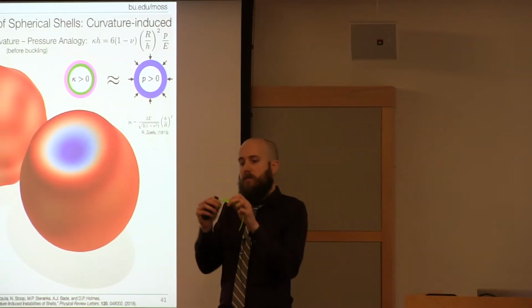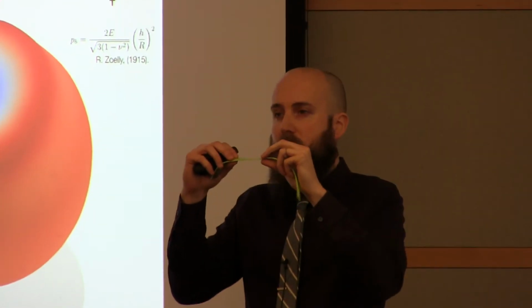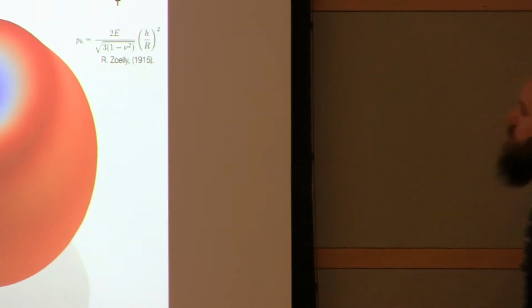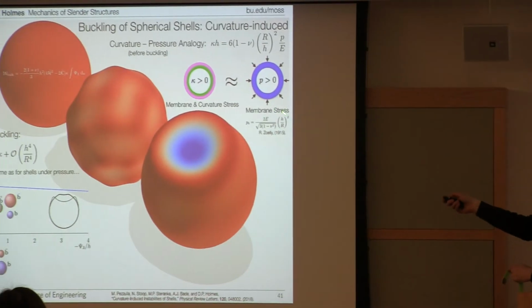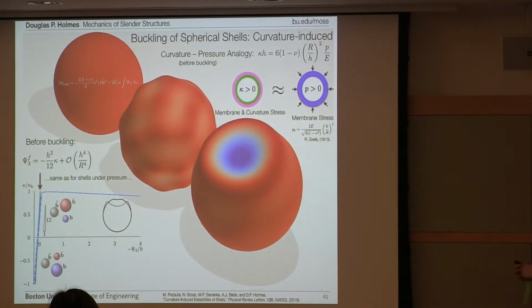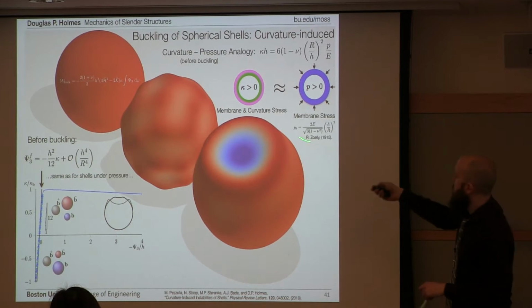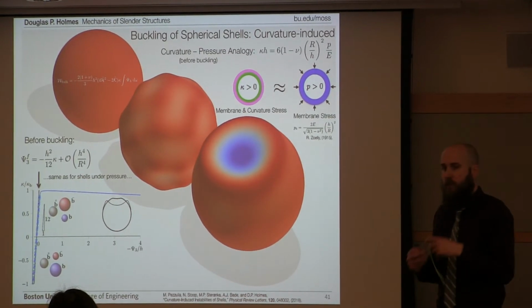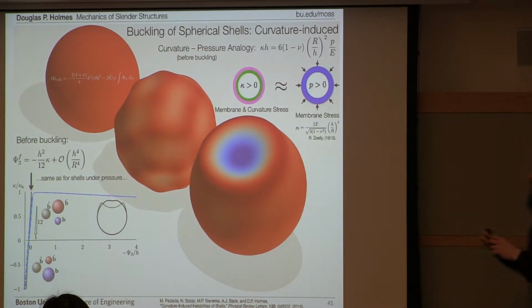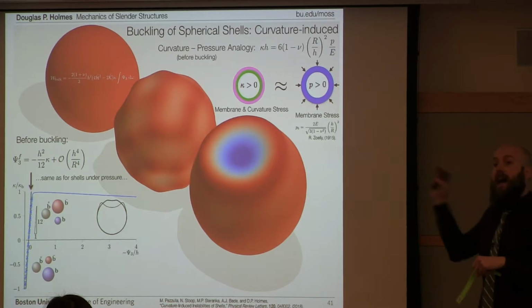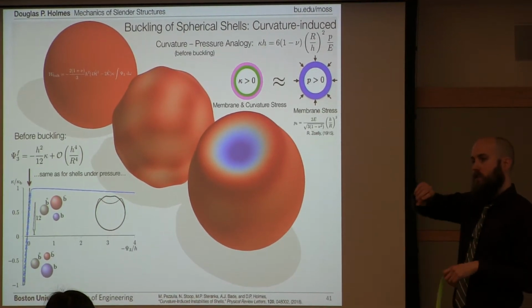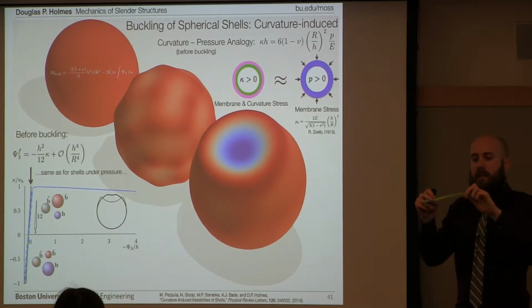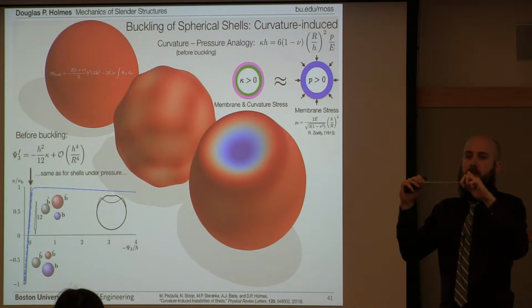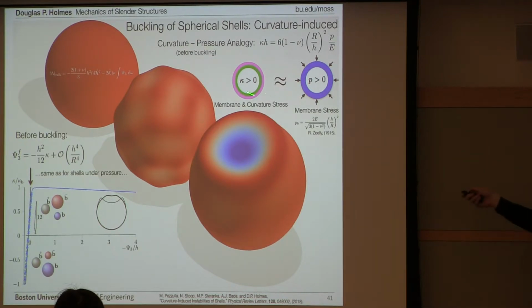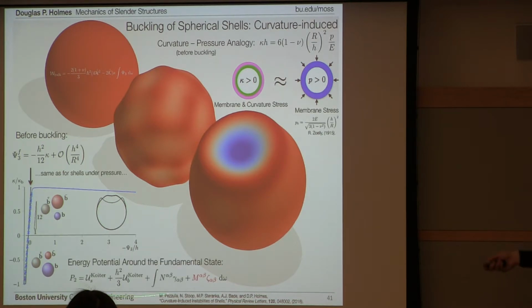What tells you when a structure will buckle is the state of stress in the material as it's being deformed. And that's very, very different. And the reason that's very, very different is because this structure is not only under a membrane state of stress, but under a membrane and a curvature stress. If you use this analogy to predict when this shell will buckle, you'll get a result that, as we say in science, is not even wrong. It will not only predict the wrong magnitude of your stimulus, but it will actually tell you that you should flip the sign. It's as if you said, when will this thing buckle? It'll buckle when I pull on it. It's completely wrong. And so if you don't consider the proper state of stress before buckling in your stability analysis, you'll completely miss this buckling instability.